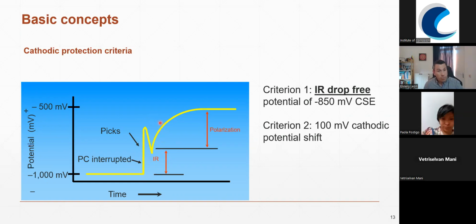To do this, and this is related already to the CIPS survey, where we need to define an on-off rate. Usually you do this by interrupting the TR with a rate of, let's say, 1 second off and 3 seconds on, especially to avoid depolarization. The exact timing will depend on the characteristics of your pipeline, the coating, the soil, or the electrolyte. It could be something like 0.5 to 3 seconds for the off time, and then the on time, something like 1.5 to 9 seconds. Again, the quicker your pipeline depolarizes, the shorter the cycle. And the longer it takes to depolarize, then you need more time to be able to have a correct reading